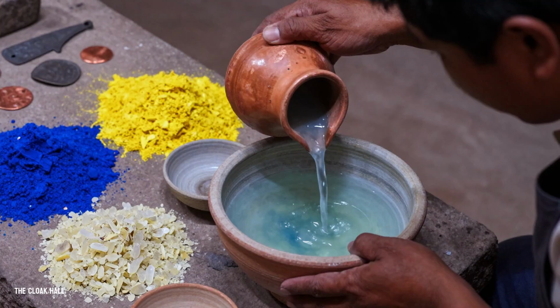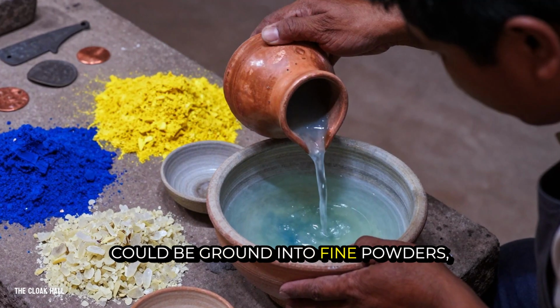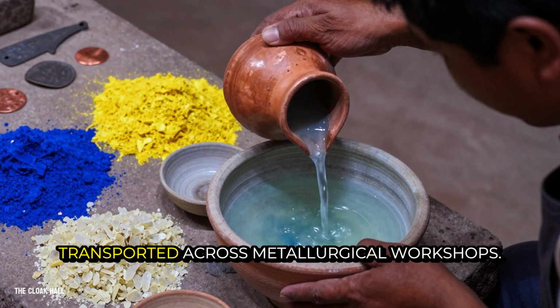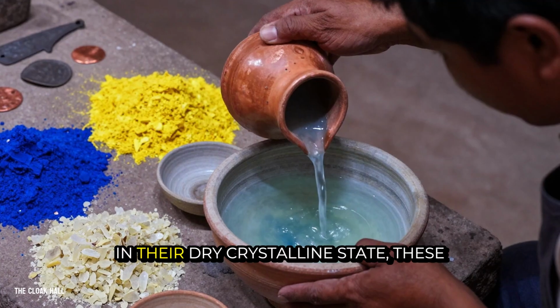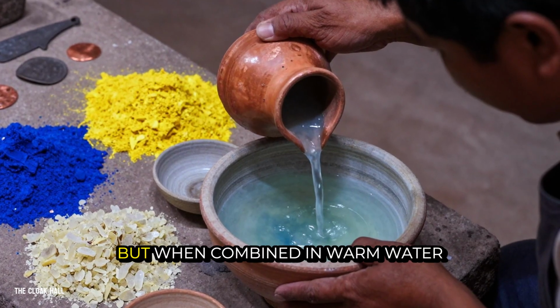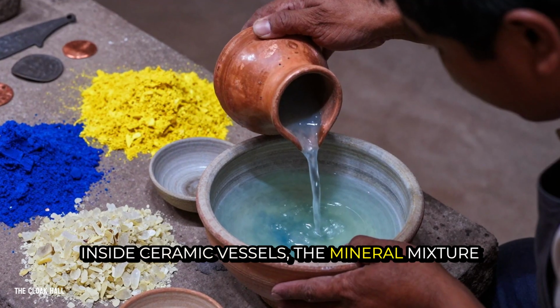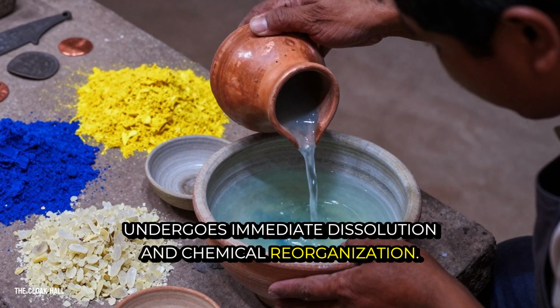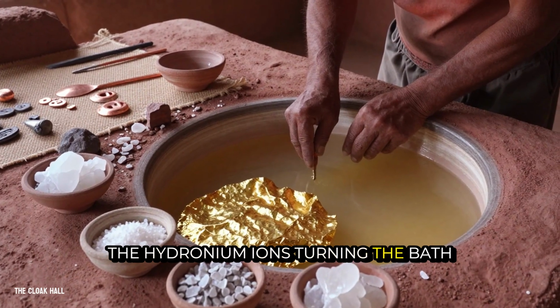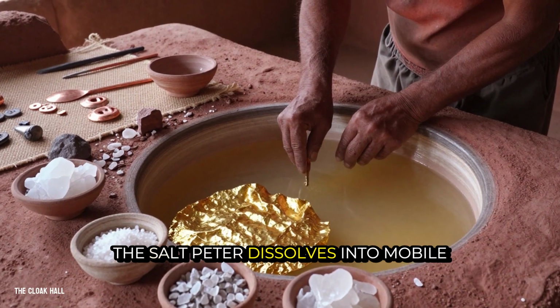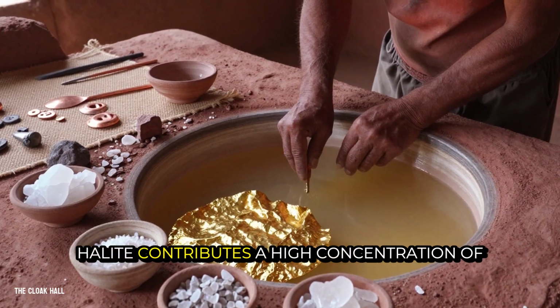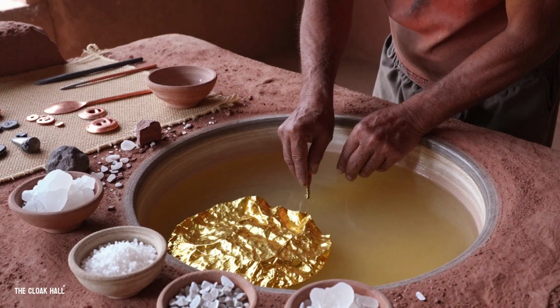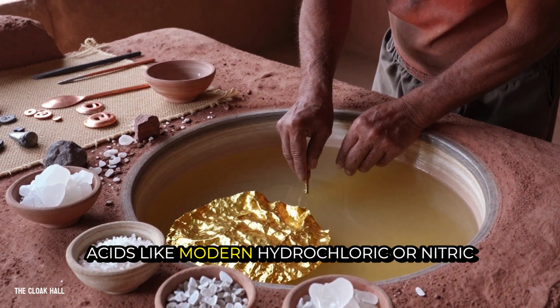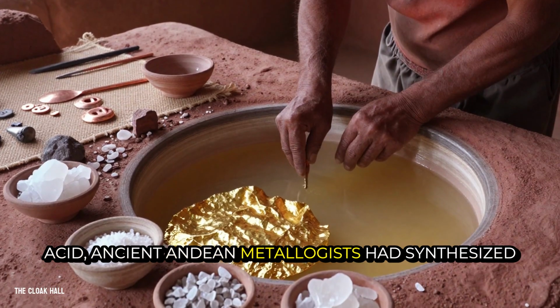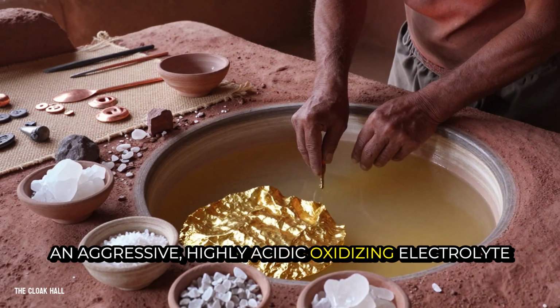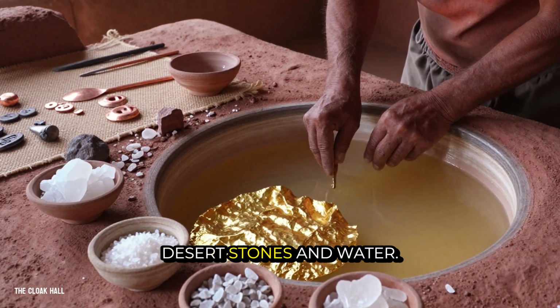When mined and dried, these minerals formed shelf-stable, crystalline salts that could be ground into fine powders, measured in precise volumetric ratios, and transported across metallurgical workshops. In their dry crystalline state, these compounds are relatively inert, but when combined in warm water inside ceramic vessels, the mineral mixture undergoes immediate dissolution and chemical reorganization. The hydrated sulfates release hydronium ions, turning the bath sharply acidic. The saltpeter dissolves into mobile potassium and nitrate ions, while the halite contributes a high concentration of free chloride ions. Without access to distilled industrial liquid acids like modern hydrochloric or nitric acid, ancient Andean metallurgists had synthesized an aggressive, highly acidic, oxidizing electrolyte solution using nothing more than crushed desert stones and water.